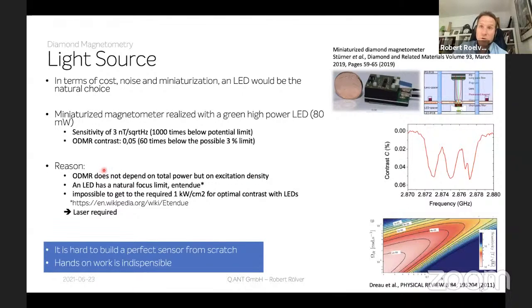does not only depend on the total power of light, but on the excitation density. So if you have a closer look in the literature, you see this nice publication where you see in a color plot the sensitivity of the diamond magnetometer depending on the optical power. This S is the saturation density, 1 is 1000 kilowatt per square centimeter, and here the omega R is the microwave power in terms of Rabi frequency. And you should go into this direction, being 0.001 of 1000 kilowatt per square centimeter, meaning you need 1 kilowatt per square centimeter to build a very good diamond magnetometer.